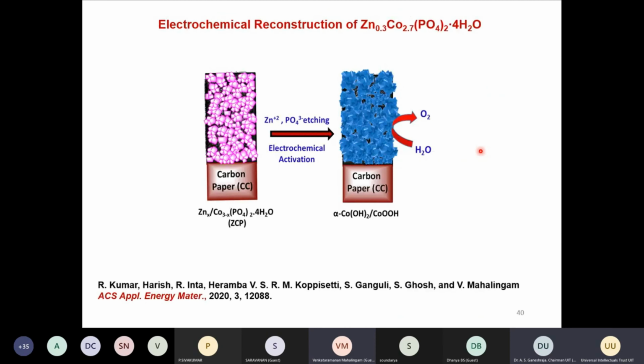So this study led us to ask whether it is only molybdenum that does this, or whether any other anion can also do this. The immediate example that came to our mind is phosphate. We prepared cobalt phosphate, of course different phosphates, and we also doped zinc into this, to see whether zinc ions can improve the activity of this cobalt. We did this directly on carbon paper, and what we found is basically the same: the phosphate etching happens. But interestingly, in this study we found that the zinc also leaches to some extent from the surface.